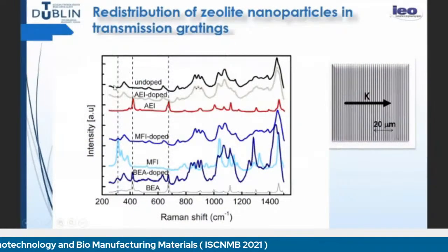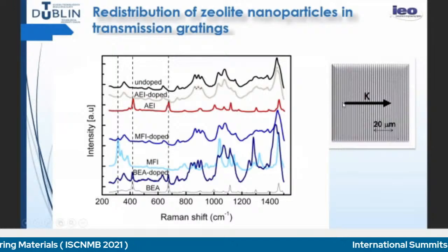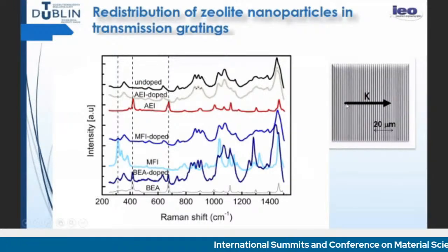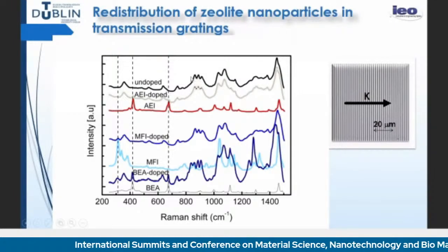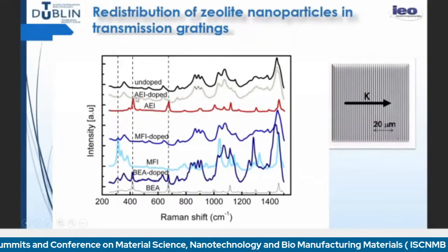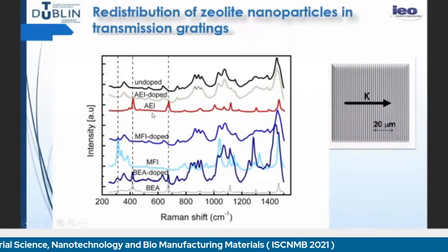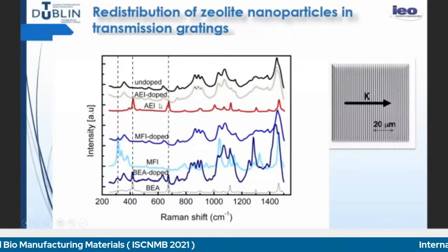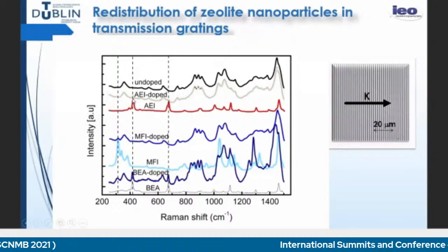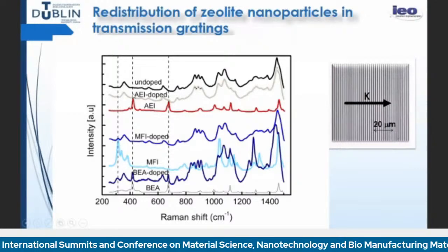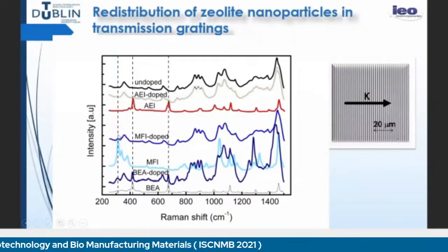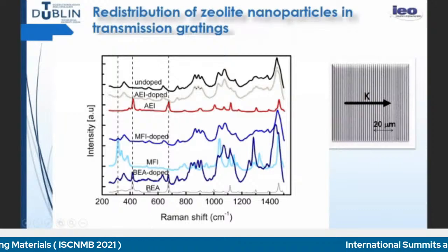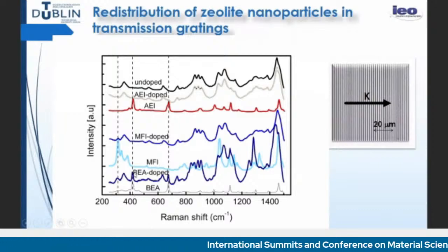Just an example of Raman spectroscopy. We record the grating and then we scan the Raman spectra along the grating vector. This is the on-top layer in black. Then we have one type of nanoparticles, AEI, and then here you see the pure nanoparticles. This peak here at around 400 inverse centimeters is not present in the photopolymer, so we have followed this peak in the mixture. For the MFI, we have followed this peak, which is not present in the pure photopolymer. And for the beta, we have followed this peak here, which is not present in the photopolymer initially.